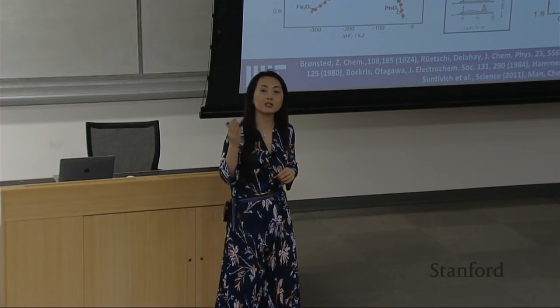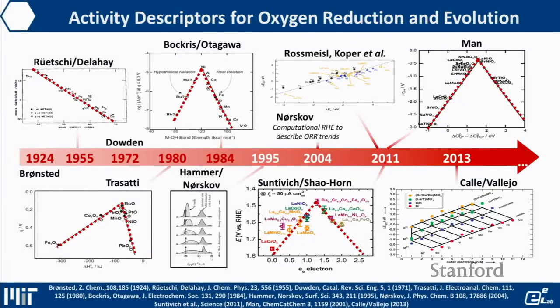Our contribution in the past decade has been looking at what type of oxide surfaces, what type of oxide electronic structure, may dictate the catalytic activity of oxygen reduction and oxygen evolution. Metal oxides are very important because if you operate in basic solution, you can use earth-abundant metal oxides to carry out oxygen reduction reactions. And metal oxides are also very important for oxygen evolution, because regardless of whether in acid, in base, or at an oxide-water interface, the catalyst catalyzing oxygen evolution is always a metal oxide.